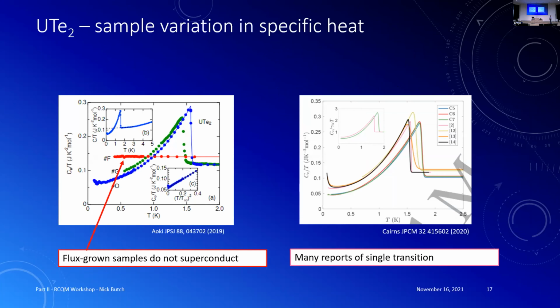Okay, so I mentioned specific heat. Since the beginning, in fact, there were discussions about what's going on with your sample. Why do you have what's typically termed a large residual heat capacity or a large gamma? And that would say that basically, we're interpreting this as an ungapped portion of the Fermi surface. I'm partly to blame because even when we wrote our first paper, it's a very, what should I say, it's a nice story to say about a half-gapped system, and you know it's inherently topological. But of course, it's met immediately with skepticism because of history. And there have been other materials where with time, quality has improved and that has gone down. I don't think that that's actually strictly parallel happening here.